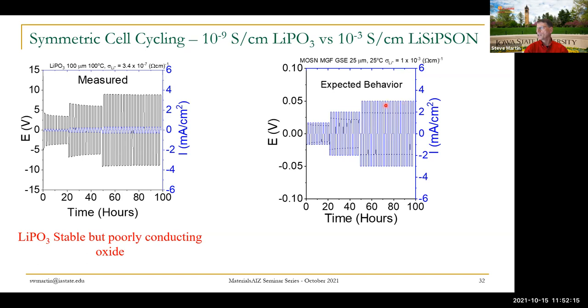You see, here's our current now way up at our 3 milliamp, but the driving voltage is only about 0.02. What that means is that a battery that gives 4 volts from a normal battery, only about 0.02 of that volt is lost internally. The IR loss is 0.02. So that's 2 parts out of 400. That's 0.5%. So very little loss. And so that bodes well for us. Once we get our compositions worked out, that we can draw them into film, we kind of expect this behavior.